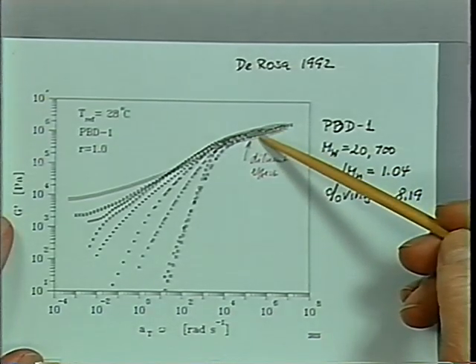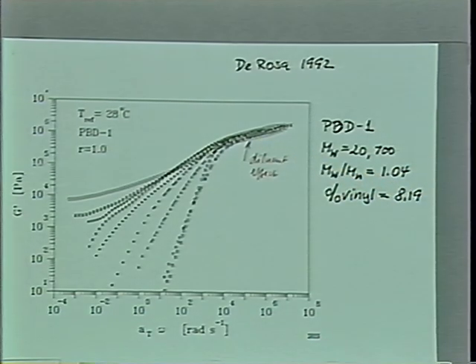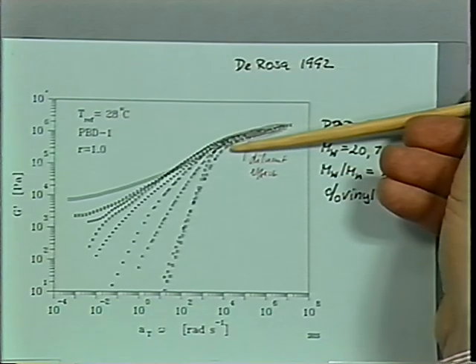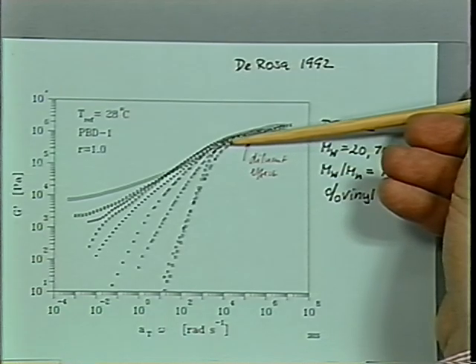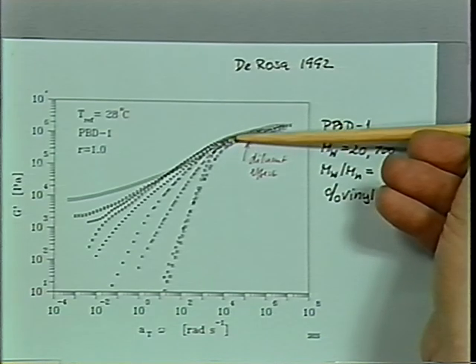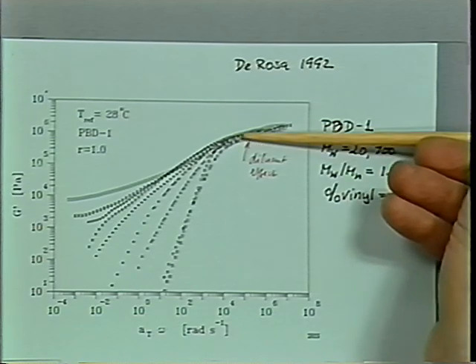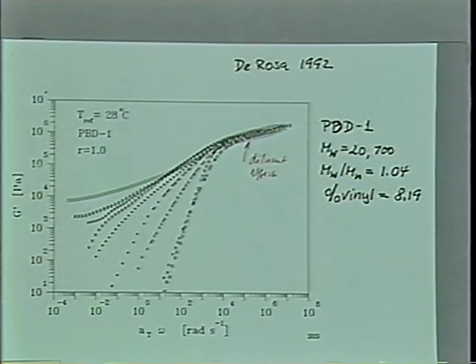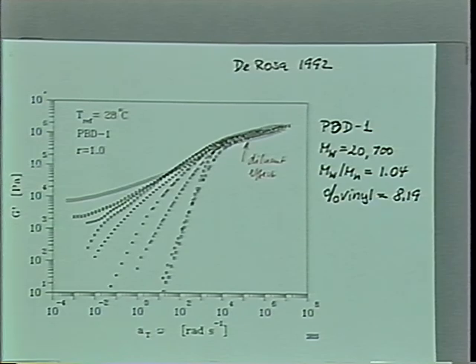Here, the solvent effect is seen. To have a stoichiometric ratio of 1, about 20% in volume comes from the crosslinker. And the crosslinker is this very small molecule. So this is acting like a solvent when you look at the system rheologically. It's mobilizing the molecules. So the solvent contribution reduces the modulus somehow. And then as the reaction proceeds, those little molecules are connected to the backbones, and the modulus is increasing like that. So this changing here is nothing else than the reduction of the solvent effect with cross-linking.